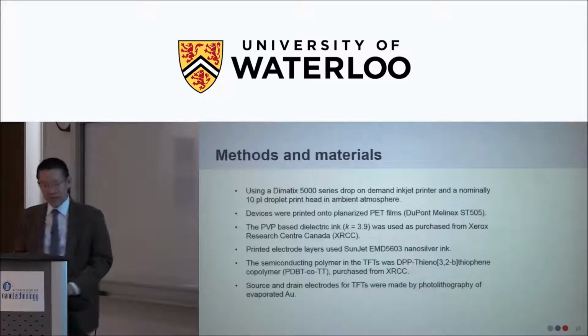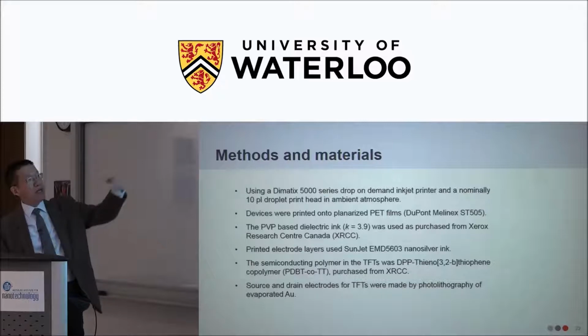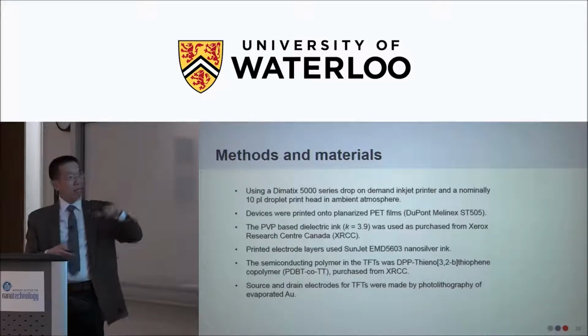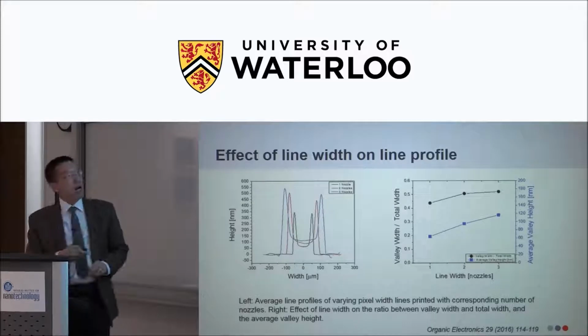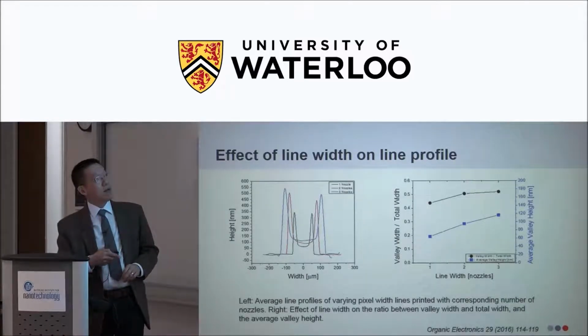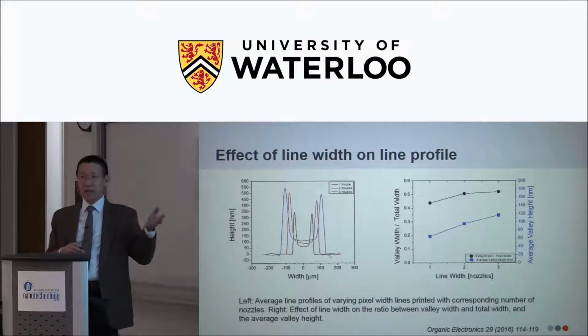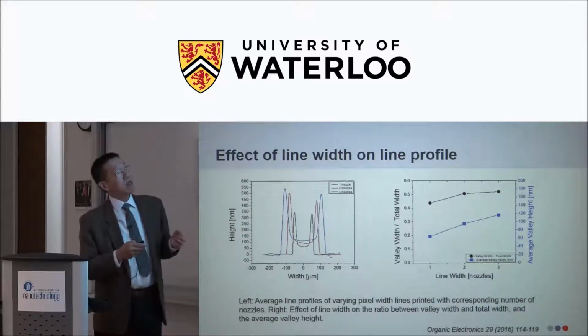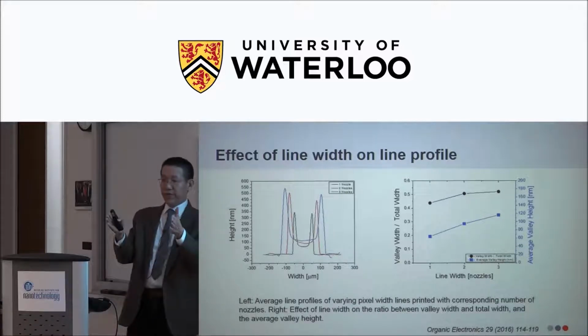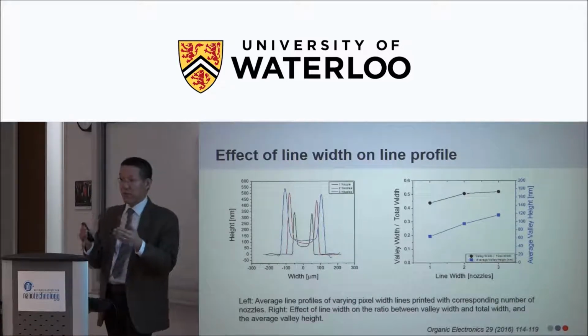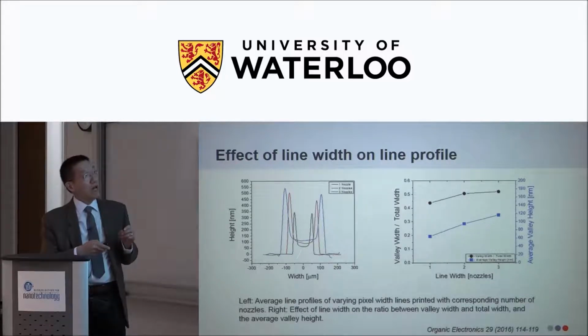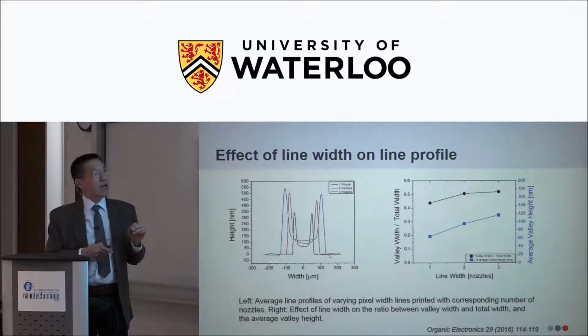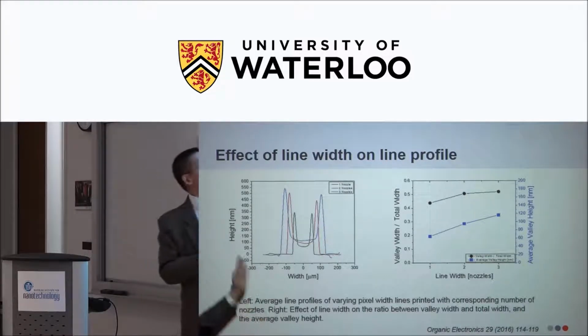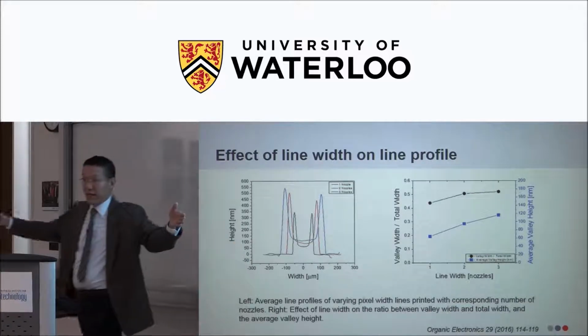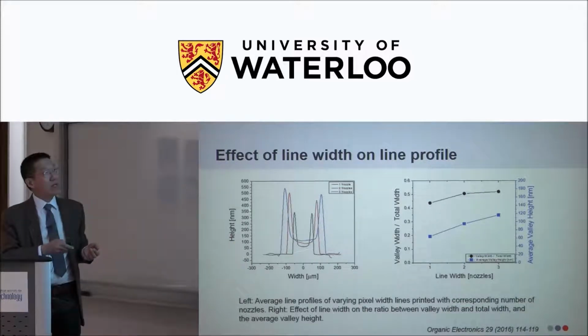So we used the inkjet printing system and bought a PVP-based dielectric from Xerox. By controlling the temperature, you'll see this is the profile of a printed dielectric layer. We use 1 nozzle, 2 nozzles, 3 nozzles to print different widths of dielectric layer. Then we control the drying process to control the width and the thickness of the dielectric layer. Don't be fooled by this profile, because there's about a 100 times difference: this axis is micrometers, this is nanometers. So they are very wide compared to the height you see here.